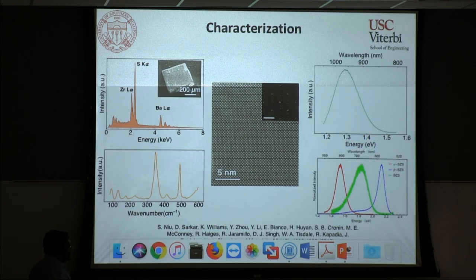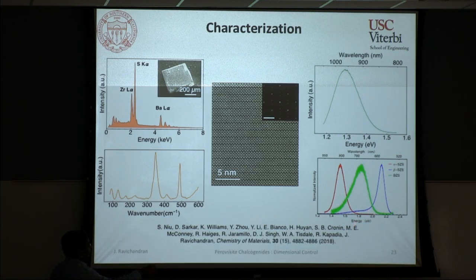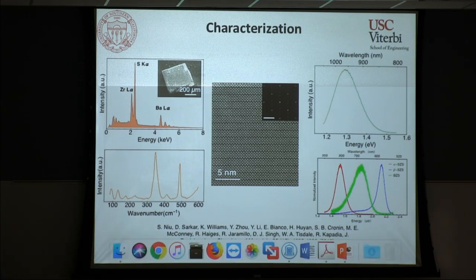So that also gave us confidence that we indeed made the right type of material. And when we did PL measurements, just like what was predicted, we did see a red shift of the peak from 1.8 eV all the way to 1.3 eV or so. So this was a very interesting point for us, and we wanted to take this further.